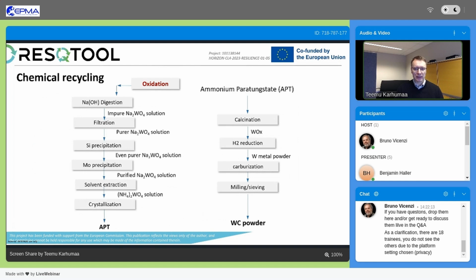solid crystalline material. And out of that, tungsten carbide is produced first by calcining this APT to tungsten oxides, reduced to tungsten metal, and then carburized to tungsten carbide. And then at the end, there are some milling and sieving steps depending on the producer and depending on the grade that is produced. So multiple times to high temperatures, creating a high amount of energy required, and complicated processes and complicated chemistry.